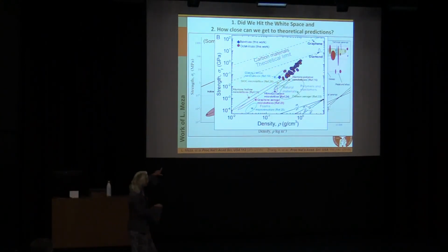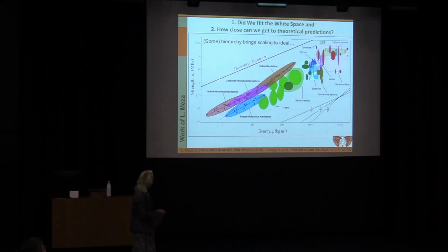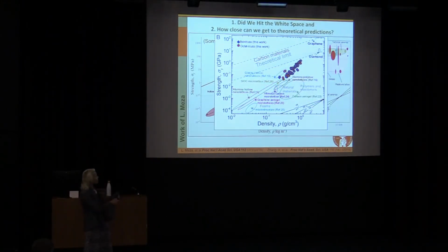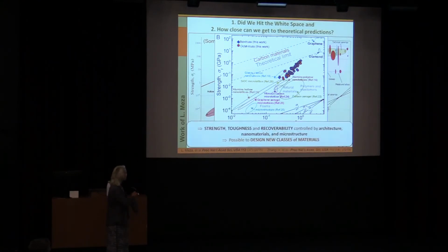And what we're learning is that at least in part of it, we can get to the theoretical limit, especially at the larger density regimes here. So here you can see we're in the lightweight regime, and we're pretty far from the theory, from where it's possible to go. But in the carbon materials, and I'll spend a little bit of time talking about this, we are in fact approaching the theoretical limit, which is very encouraging. All right, now,